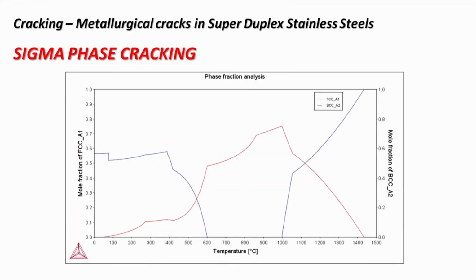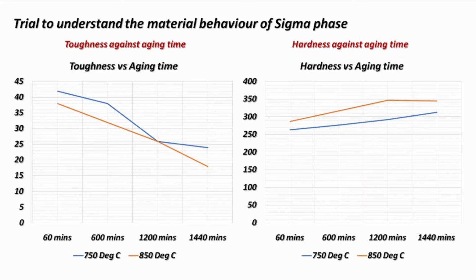Yes. So this blue line indicates the ferrite phase and the red line indicates the austenite phase, where you can see between 600 to 1000 degrees Celsius, we have no ferrite, indicating the formation of sigma is high between these temperatures. So further to understand, we did some other trials at 750 degrees Celsius and 850 degrees Celsius, showing a fall in impact toughness with increase in hardness. And the ferrite phase gradually decreases because the sigma phase forming in the material is a non-magnetic phase, so we can easily identify the sigma phase using the ferritoscope.